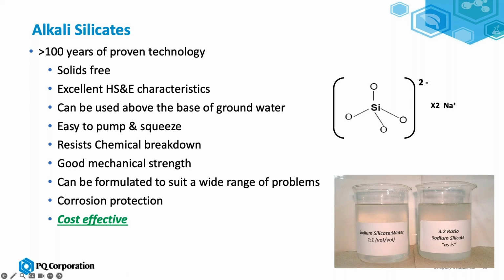As far as viscosity goes, in the picture on the bottom, you have what's called a 3.2 ratio. That would mean for every 3.2 pounds of sand, there'd be 1 pound of soda ash. As is, that's about 180 centipoise. Cut 1-to-1 with water, it goes down to about 20 centipoise, and that's at room temperature. So running a 50% solution, you're pumping a very small molecular weight species with a very low viscosity. So very easy to pump in place. Upon setting, it has excellent chemical resistance, very good mechanical strength, and we can formulate over a wide range of properties depending on what's required. And then the other benefit of running with silicates is it offers excellent corrosion protection. And as far as cost goes, it's very, very effective.